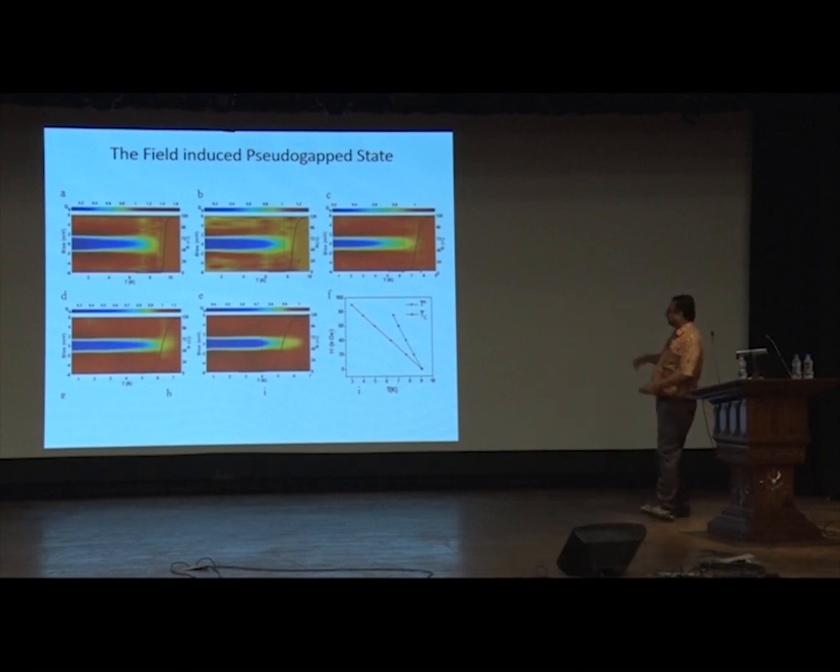And if you are in this disorder range, in magnetic field, quantities like upper critical field are no longer defined in the conventional Abrikosov sense. In the conventional Abrikosov sense, the upper critical field definition is only applicable in a clean system where you form a very well ordered lattice.